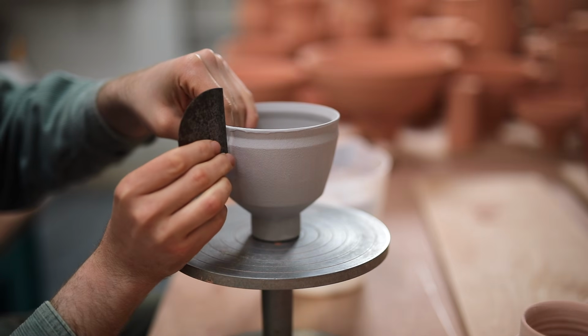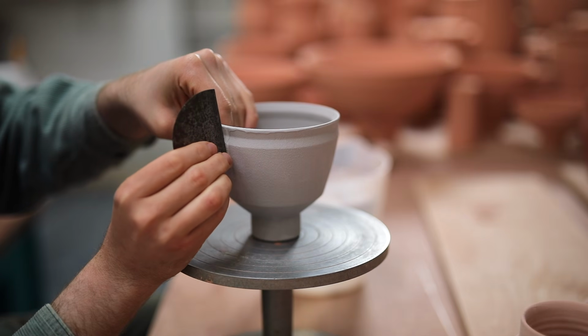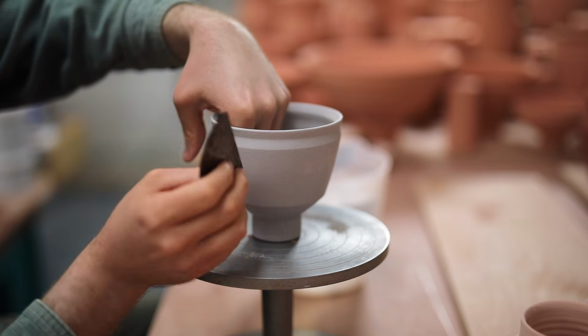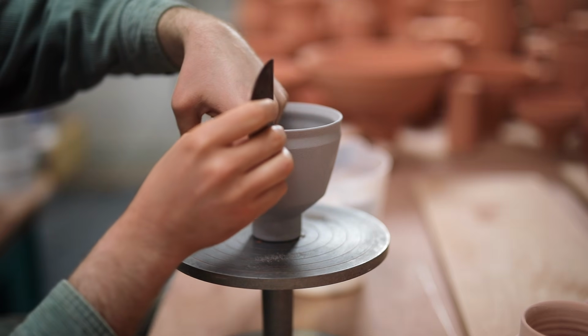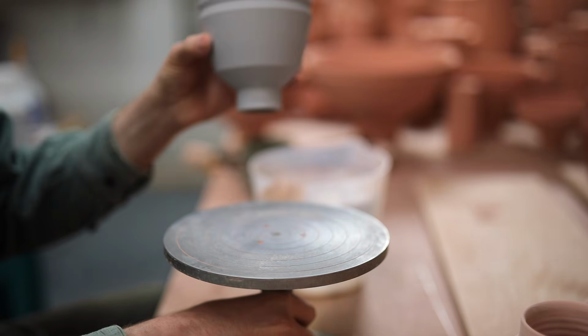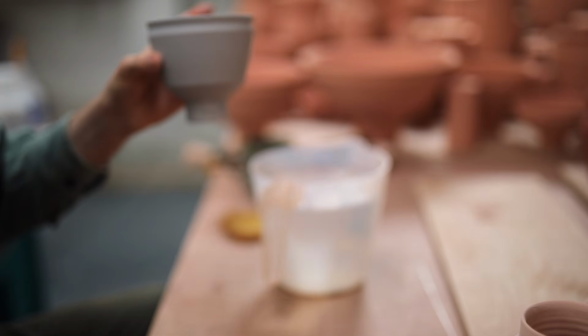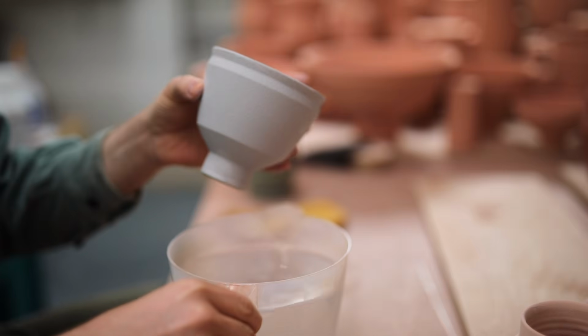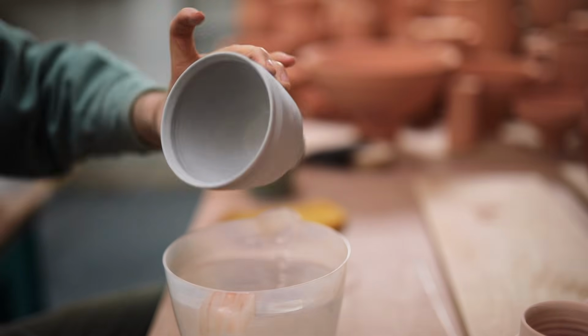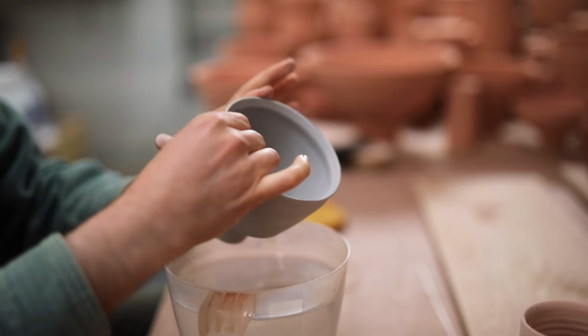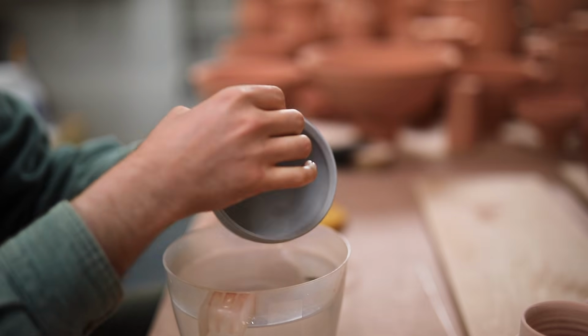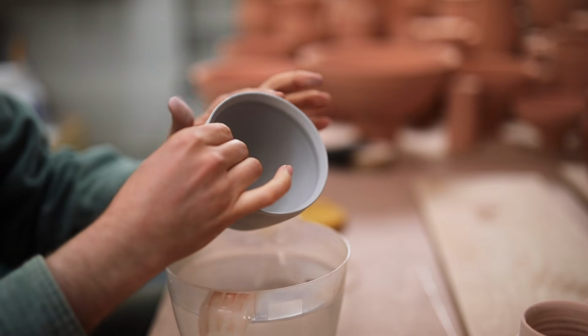Essentially, I want to get rid of any drips or thick spots that cover the surface. There was a slight amount of overlap around some of the rims, but this was only bad on one of them, in my attempt where I poured that inner glaze out more slowly, which gave it more time to roll around the rim and spill over the outside. The quicker I was when tipping the glaze out, the neater the glaze around the rim was.